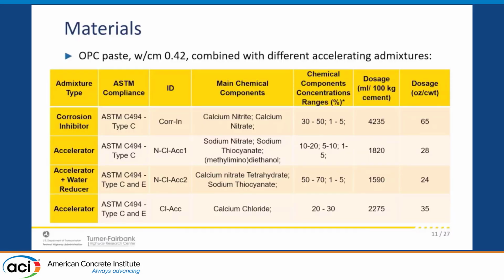So these are the type of accelerators that we used during our study. You can see that the first one, for example, is a corrosion inhibitor, which also acts as an accelerator. There's a little bit of concentration information - every one of these different admixtures has different chemical components, different recommended dosages. What we typically adopted in this study was about 50% of the maximum allowed or the maximum recommended dosage from the supplier for this particular admixture. So we're around 50% of the maximum dosage.